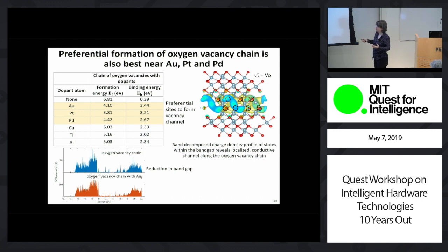And again, we see that with more electronegative ions like gold, platinum, palladium, the ease of forming such a vacancy channel is easier compared to the undoped case or compared to the copper, titanium, aluminum case. And similarly, the binding energy is stronger in this case. So both of these numbers tell us that there is preferential formation of oxygen vacancy chains along the paths where you have the gold, platinum, or palladium implanted ions.